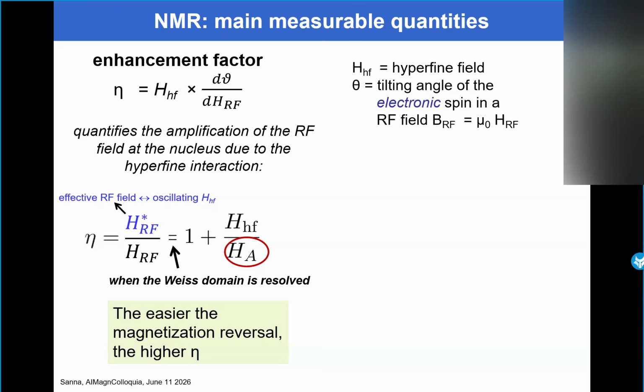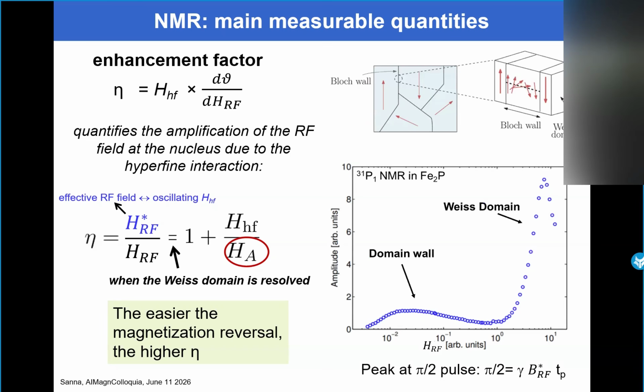So, in order to give you an example of how this works, I can show you here this experiment, the NMR signal amplitude on phosphorus in this hard ferromagnet as a function of the intensity of the radio frequency field, or if you like, of the power transmitted by the coil. And you see here that you have two different spectra, one for lower values of this radio frequency field and one for higher values.